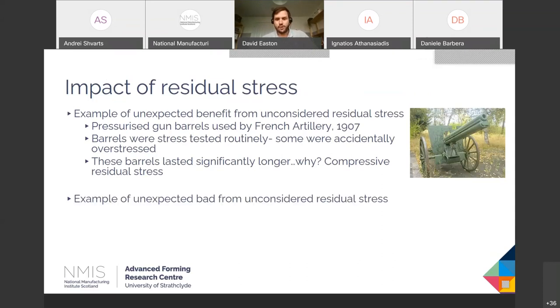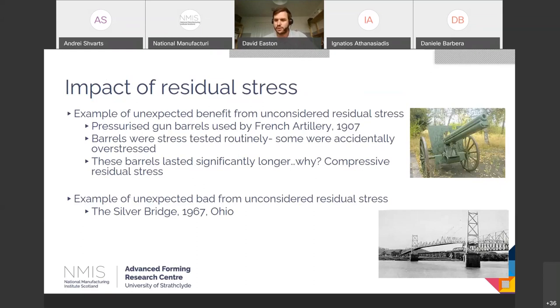Unfortunately, it's not always good. If we don't consider residual stress, bad things can happen. And an unfortunate example of this would be the Silver Bridge in Ohio in 1967. So this bridge had actually stood for decades, seemingly fine, until one day a crack in a single eye bar caused the bridge to collapse, sadly causing the death of 46 people.